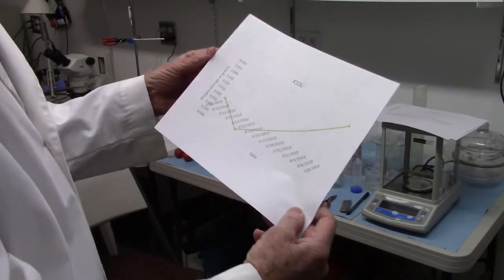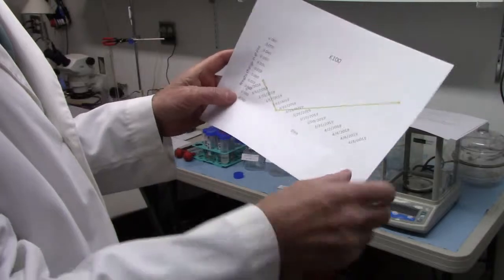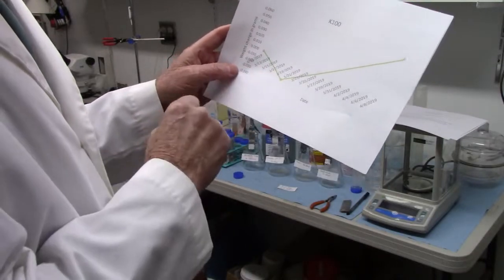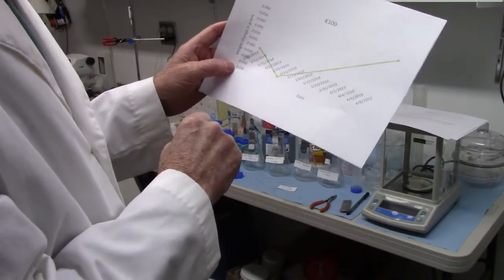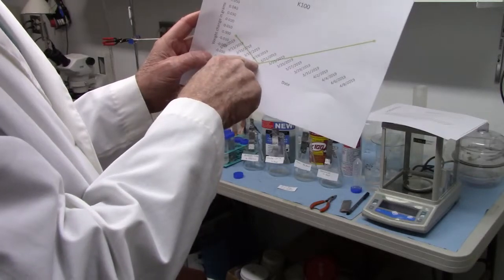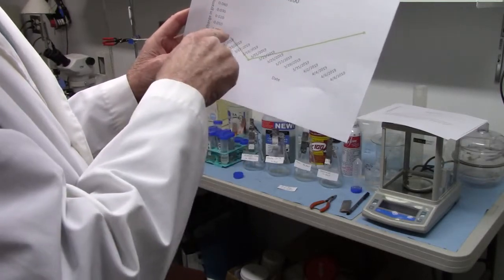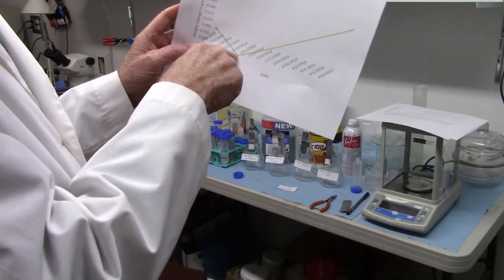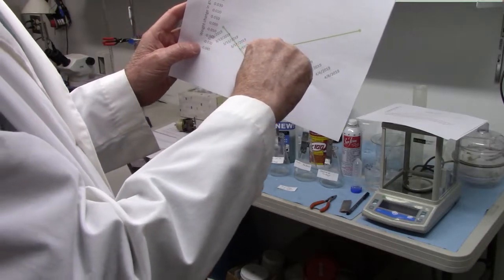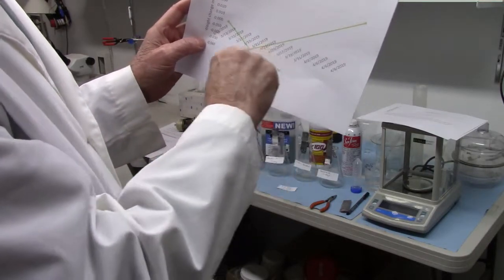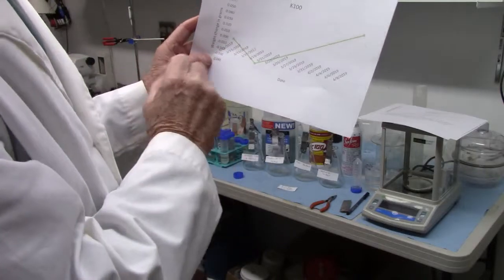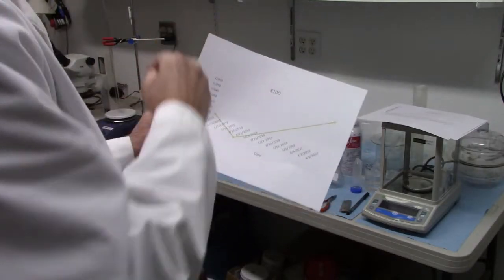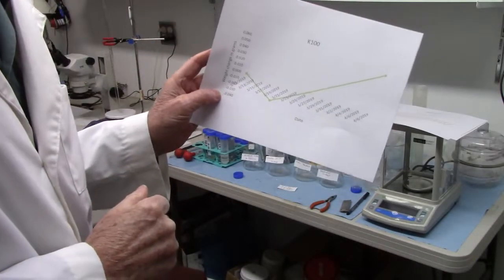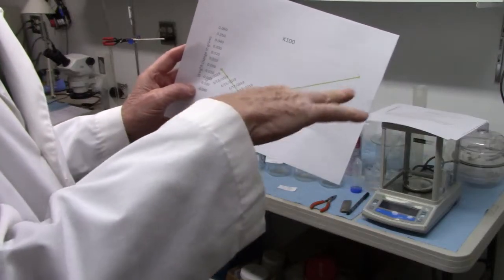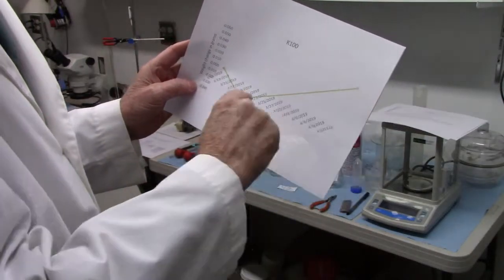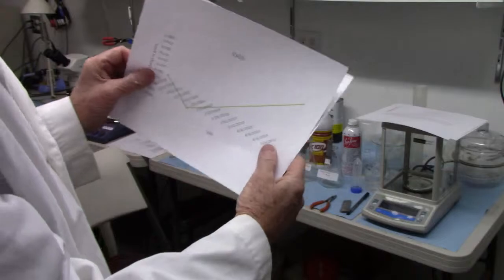The K100 in seawater, initially, for the first 7 days, it lost weight. And then it progressively increased in weight. I could assume that whatever is in K100 to provide corrosion protection was gradually building up on the surface, and that would account for the increase in weight.